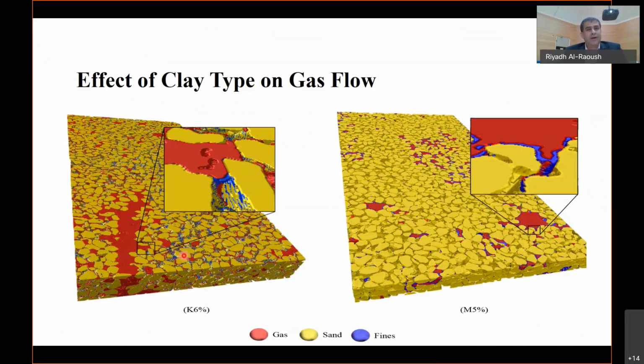This is a zoom for the type of behavior that we see if we inject clay in our system. You can see that it gives us information about the clogging behavior. On this image here, the clusters of clay or kaolinites are observed to be attached at the sand-water interface. So we can identify what type of interface we have here. And this causes clogging of small throats, which in turn gives gas-induced microfracture. However, on this image here, montmorillonite is observed to be attached at the gas-water interface, and that causes a disconnected gas phase.